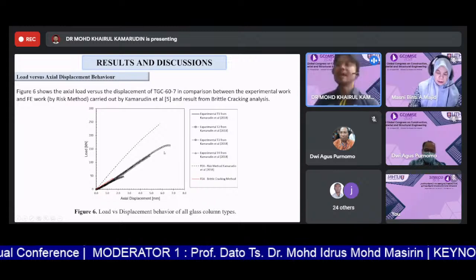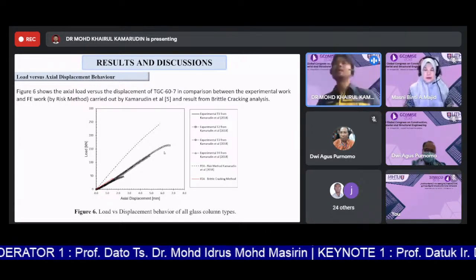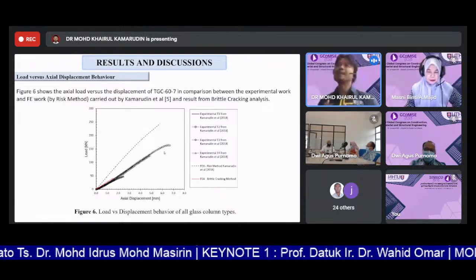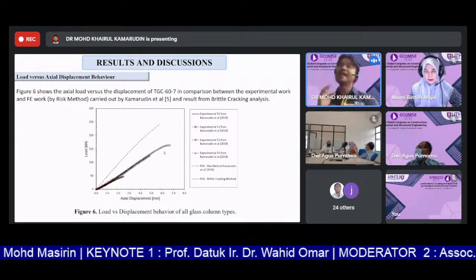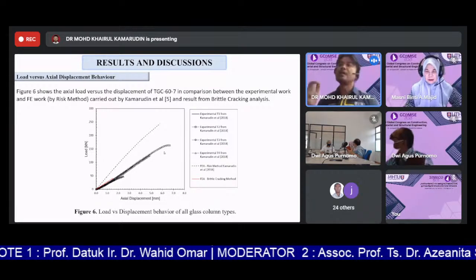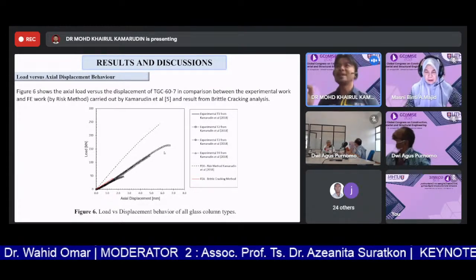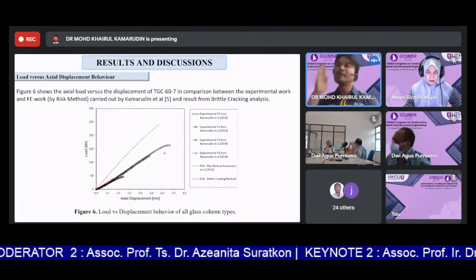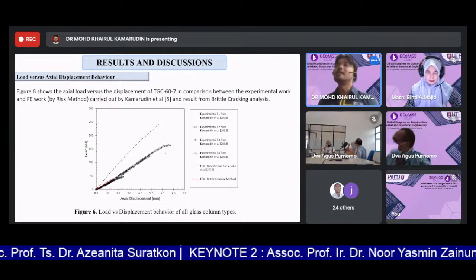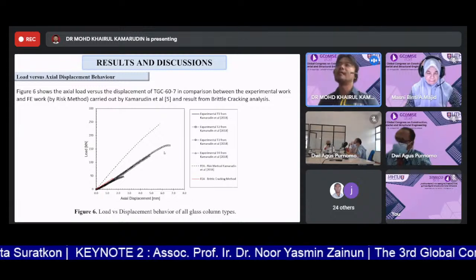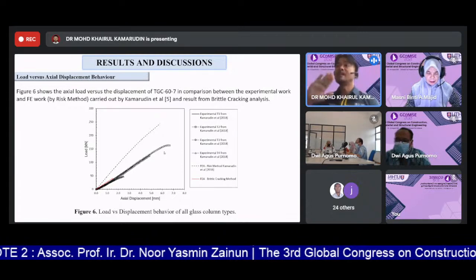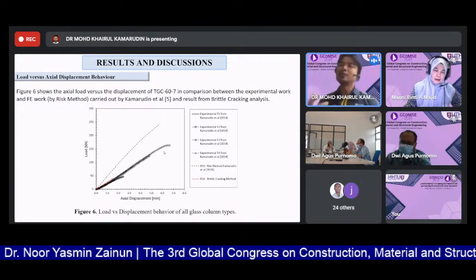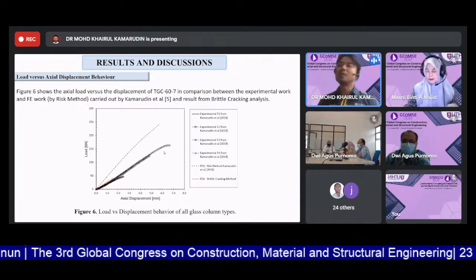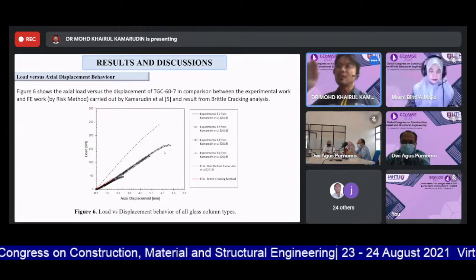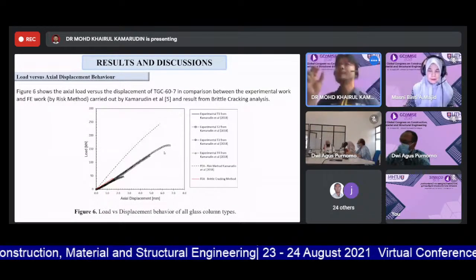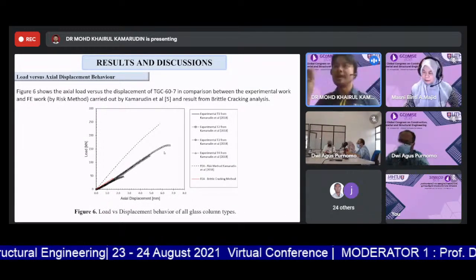But as a justification here, we do understand that for glass specimens, we cannot take the result as an average, because each glass, even if they have the same geometrical dimensions, has a unique character that cannot be quantified, which is the initial surface crack on the glass. That initial crack cannot be quantified yet. We are now trying to come up with a methodology to quantify the initial cracks on the surface of the glass, which are the flaws. So we wanted to have that in mind to conduct this analysis further.